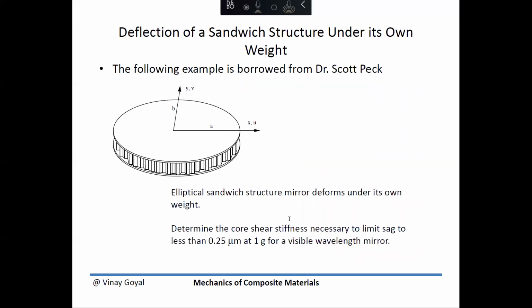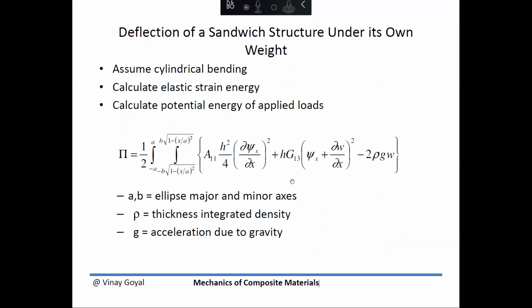Let's look at this example by Dr. Scott Peck, where the deflection of the sandwich structure is analyzed under its own weight. The elliptical sandwich structure mirror deforms under its own weight. We want to determine the core shear stiffness necessary to limit the sag to 0.25 microns at 1 G for a visible wavelength mirror. We will use the energy method calculation again. Once again, we're going to use cylindrical bending assumptions, which is basically going back to beam bending. We'll calculate the total potential energy, which is given by this equation.